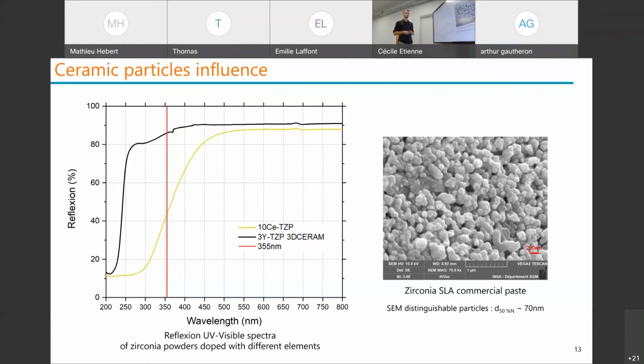You have much more absorption, and I told you that we have 50% of the volume which is filled by the particles. So you can imagine how it works on polymerization. So it changes a lot how it behaves. And we have thought of techniques to avoid this absorption and the change of the polymerization, maybe by functionalization or by making core-shell structures. So we will do that after on the powders.